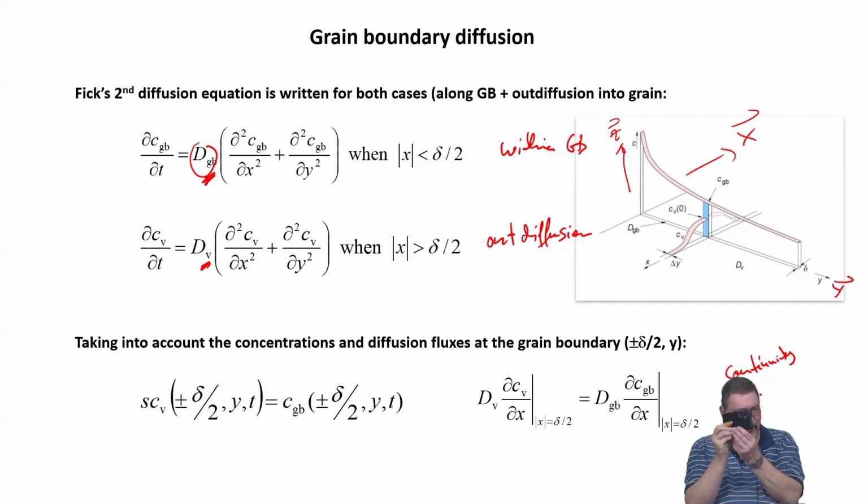This is the grain boundary plane. And this is the plane where I applied the tracer. So what matters is diffusion along the boundary. This will be the same here as here, because I applied tracer everywhere, right? So it means we linearize the problem because the diffusion flux along the boundary is only going along the boundary. And this or this doesn't matter, right? And this helps us to